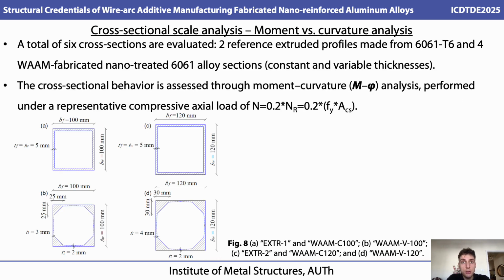The analysis will be conducted in 2 scales. First of all, we will do a cross-sectional scale analysis, conducting a moment versus curvature analysis for the examined section. We will evaluate a total of 6 cross-sections. Specifically, there will be 2 reference extruded profiles made from typical 6061-T6 alloy, and there will be 4 WAM-fabricated nano-treated 6061 alloy sections. These sections will feature constant and variable thickness to demonstrate the advantages of 3D printing or additive manufacturing. The cross-sectional behavior will be assessed through moment curvature analysis performed under a typical and representative compressive axial load of 0.2, or 20%, of the axial load capacity, which is equal to the yield stress times the cross-sectional area.